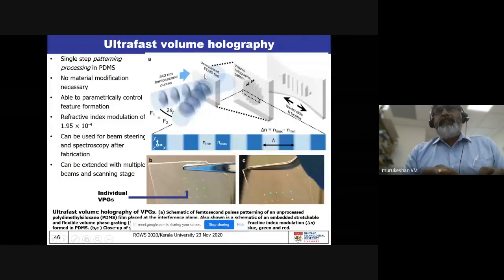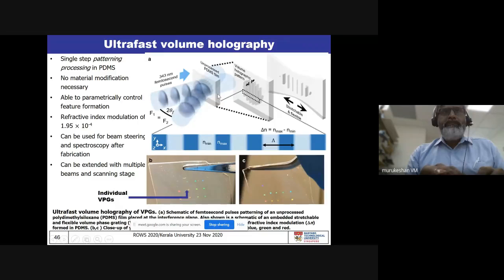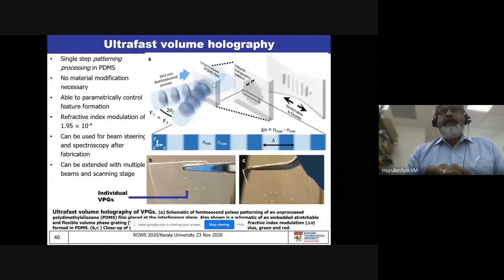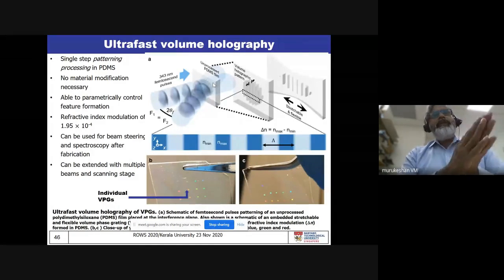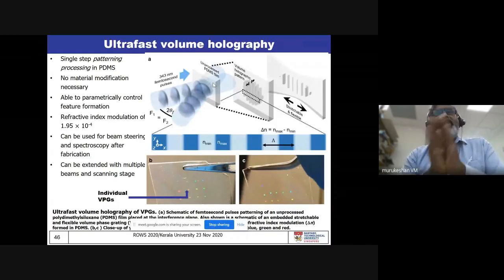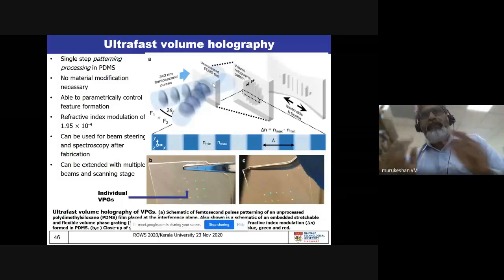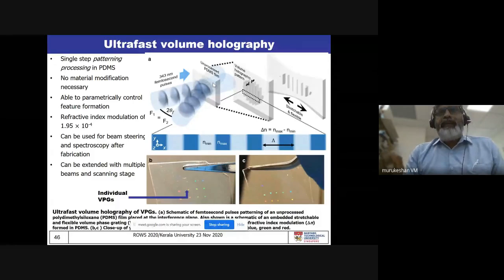And the material that is used is actually a PDMS, an unprocessed PDMS without any manipulation, okay? The raw. And then we were able to get a volume holographic pattern, which means that the thickness of this is actually larger than the wavelength that is going to be used there, okay? When you are meeting that criteria, you are already going from the Raman-Nath regime to the Bragg regime, and you are going to get a nice Bragg condition there for Bragg diffraction, etc. Okay, and that is what we are going to discuss here.